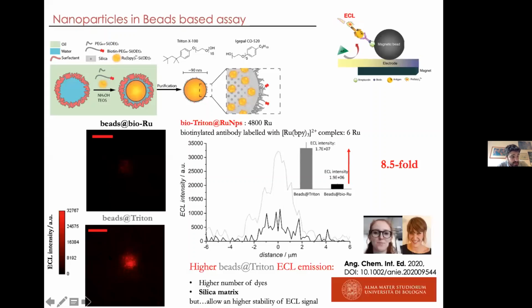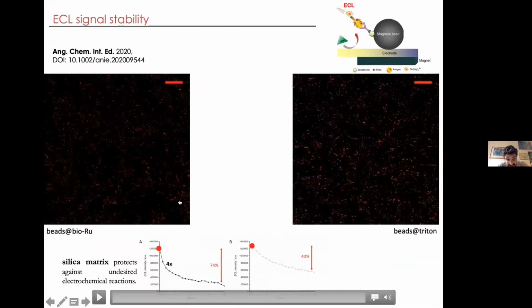And this is electrogenerated chemiluminescence, so electrochemiluminescence, beads emission experiments, and you can see that we have around 8-fold increase when we use nanoparticle instead of the standard ruthenium dye. This is a different synthesis, but I don't have time to go into detail on this. But what I have time for, and I must go into details, is the stability.